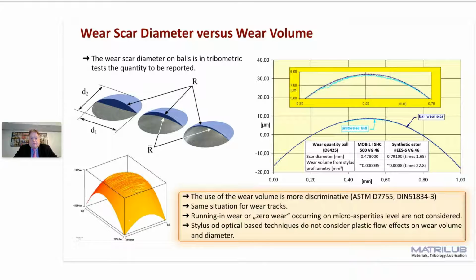On the right side, you see a little bit what can happen. This is a trace with a stylus profilometer at the center of a wear scar. You have in a darker color the initial shape, and the light blue shows you what in reality happened. It means you had in this case only the elastic deformation on the ball. The lubricant worked and protected very well. But if you look from the top, you see a scar diameter because tribofilm on the surfaces was deposited, but in reality, wear is minimal.